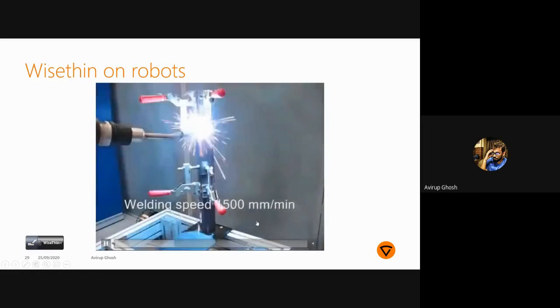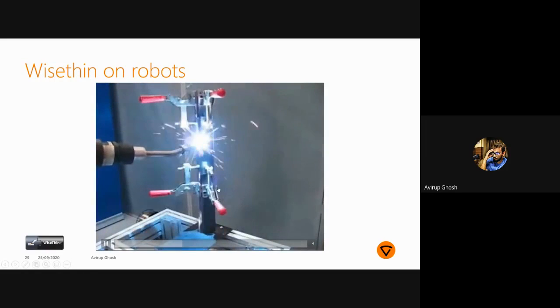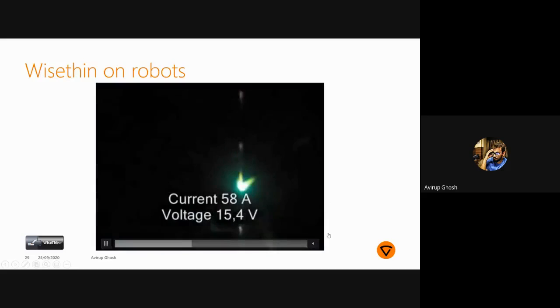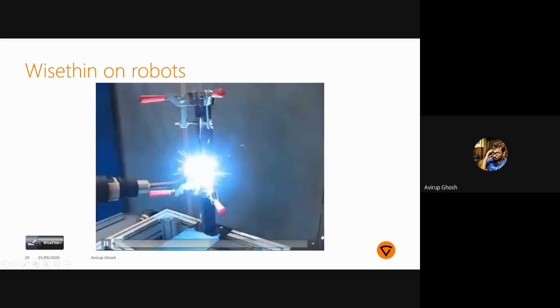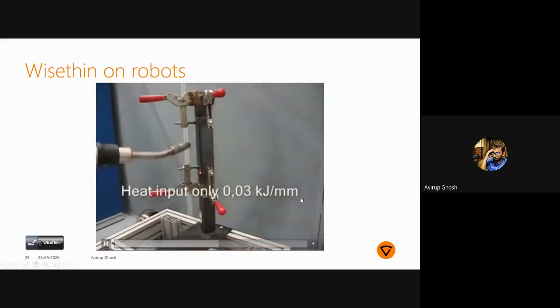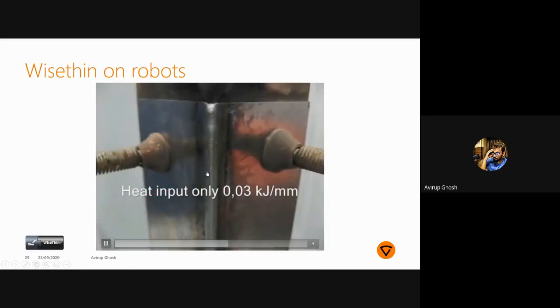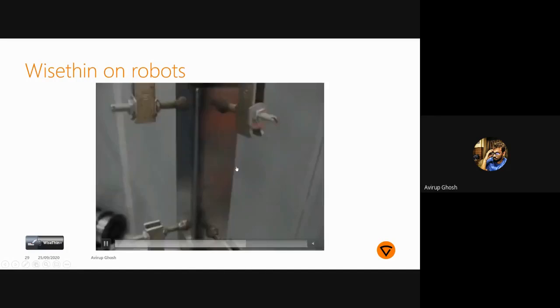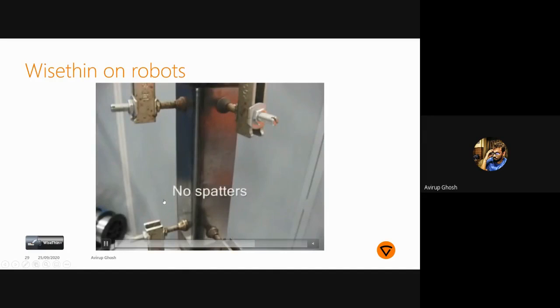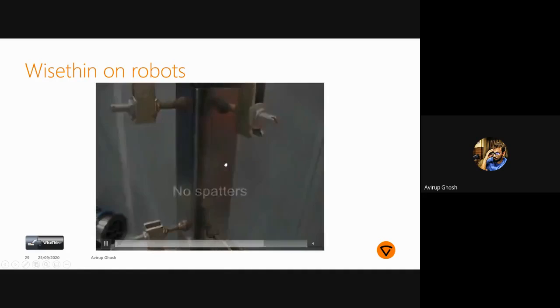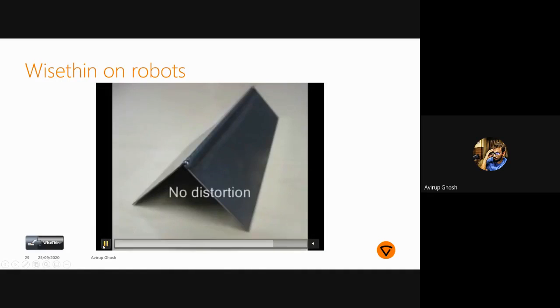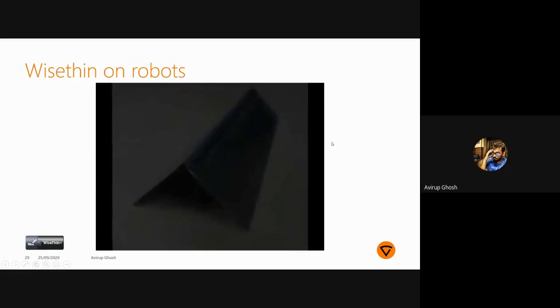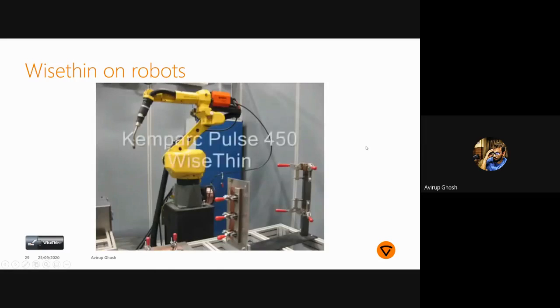The welding speed is around 1.5 meters per minute, and we are going downhand. The total heat input is around 0.03 kilojoule per mm. And practically speaking, you can basically touch the material just after welding also. How does this happen? I'll go to the next slide.